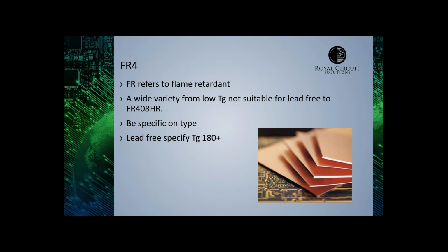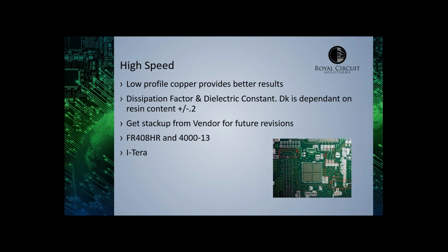So if you're calling out for lead-free, you want to specify a Tg of 180, or even just specify on the print that this must be suitable for lead-free applications, and we'll know what that is. At Royal Circuits, all our multi-layers we do on high temp FR4. The only time we'll use low temperature material that's not good for lead-free is for double-sided, and if the print specifies it isn't required.